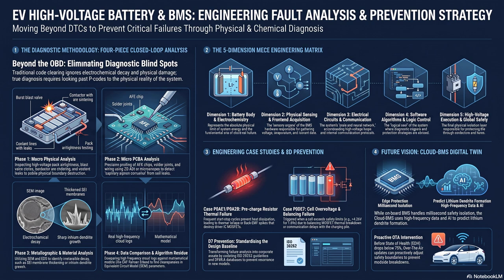So, if an engineer uses a scanning electron microscope, an EDS, and they observe that the SEI layer has grown excessively thick and is hoarding lithium, that provides objective, undeniable proof that the battery has permanently lost capacity. It is not a software glitch. The battery has chemically aged and degraded. It's like finding out the fuel tank on your car physically shrank. That's exactly what it's like.